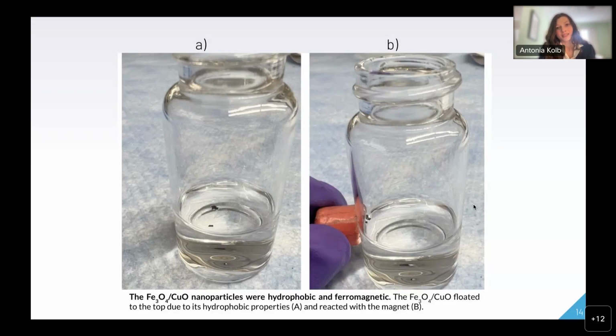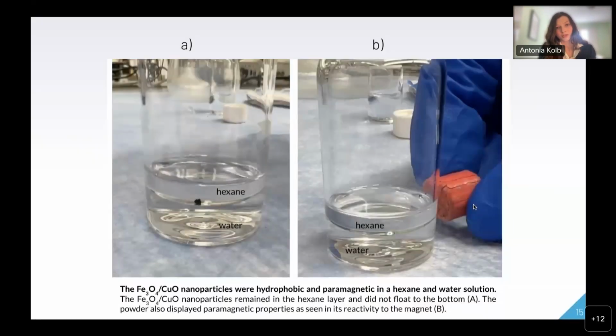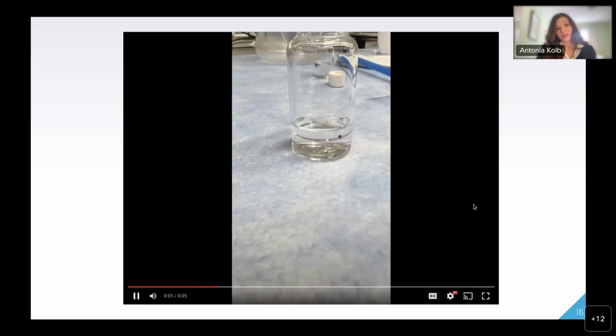Then, the powder was tested in a hexane and deionized water solution. Hexane was tested because it is a compound that can be found in spilled oil and therefore was used to simulate an oil spill. The powder remained in the top layer of hexane and did not sink to the bottom layer of water. It once again, as expected, displayed magnetic properties and was drawn to the magnet. Here is a video displaying these ferromagnetic and hydrophobic properties.